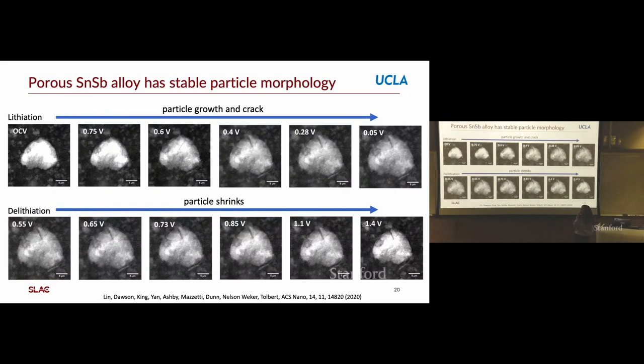And so this is one example of many particles of the tin antimony porous material. Starting with the lithiation cycle, you have a small volume expansion. We actually see some cracking at about 0.6 volts and 0.4 volts. So there is some cracking, which was a little disappointing, but not much areal expansion. And then you returned to the area that we started with when we took the lithium out. We can plot that again.